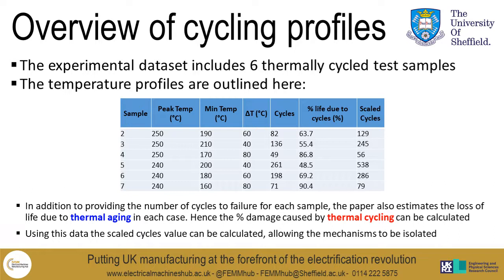Using this, it's possible to scale the values to calculate what the estimated number of cycles could have been if thermal aging wasn't a mechanism which was also acting on the samples. This is particularly helpful when considering things in FE, as the FE model doesn't consider thermal aging as part of its failure mechanism.